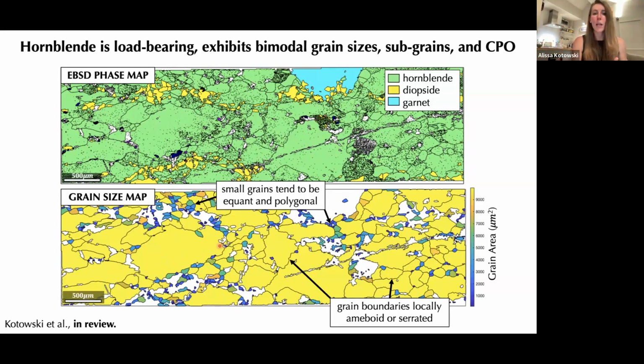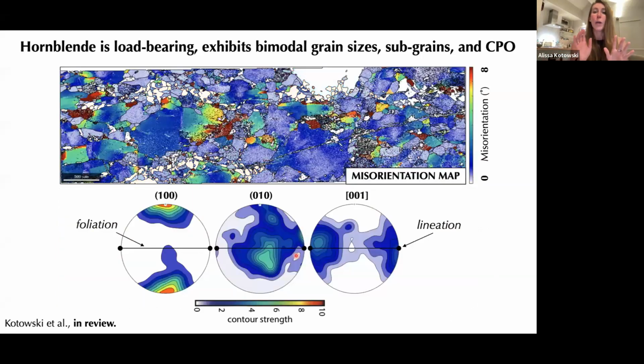So we see big yellow grains of hornblende surrounded by small blue grains, and these small grains tend to be equant and polygonal in shape. The boundaries between the big grains tend to be amoeboid and locally serrated. We can also look inside of the grains and look at the patterns of intracrystalline plasticity in them.